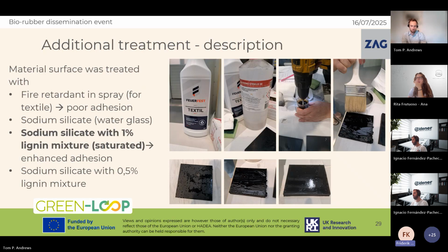And then, of course, we were looking at what we can do. We have selected three types of, let's say, fire retardancy or surface treatment that could actually help a lot in reaction to fire properties. So we first said, okay, let's use a commercial one that is available and apply it. The second one is use water glass or sodium silicate. And the third solution was use water glass, but also add some lignin inside to the surface.